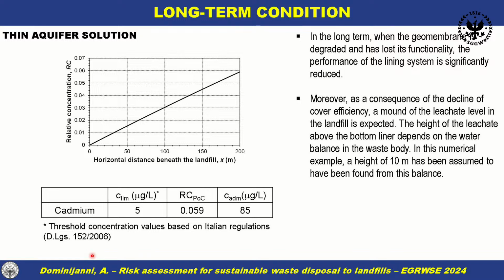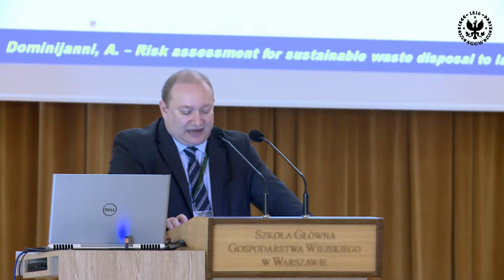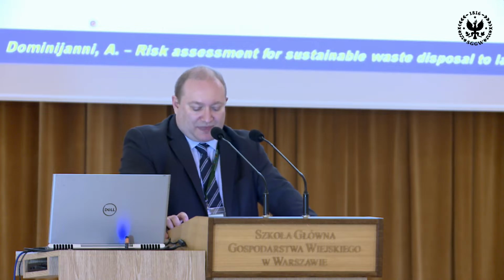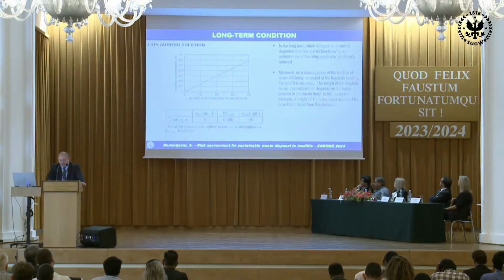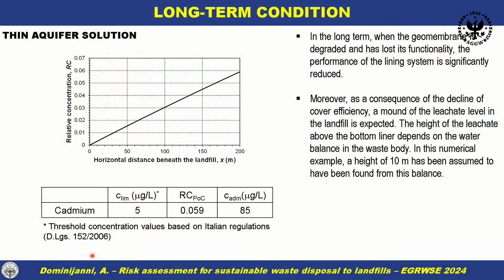The second considered scenario is that in the long term, when the geomembrane is degraded and has lost its functionality. Under such conditions, the performance of the lining system is significantly reduced. Moreover, as a consequence of the decline of cover efficiency, a mound of the leachate level in the landfill must be expected. The height of the leachate above the bottom liner depends on the water balance in the waste body, and in this numerical example, a height of 10 meters has been assumed to have been found from this balance.